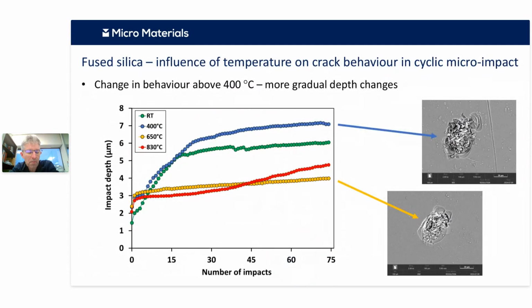And you can look at more brittle systems. In this case, this is fused silica glass, which, as Vineet said, has a slightly unusual, anomalous temperature dependence of elastic modulus. And interestingly, its fracture behavior also undergoes clear transitions. In this case, these are just cyclic tests at the same position, but you can see a clear difference in behavior when you test at 400 degrees and below, and then at 650 degrees you're getting a transition into a much more gradual damage deformation mechanism.